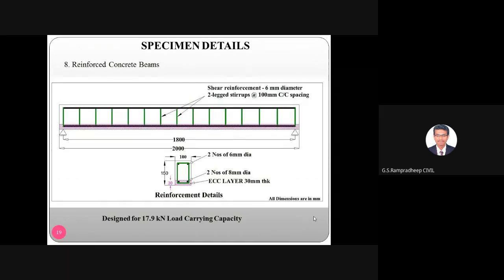And he went for the flexural beam analysis, where you can see the length is 2 meters outer to outer, and from center to center 1.8 meters, a clear span of 1.8 meters. He used 2-legged stirrups at 100 mm spacing center to center, with 6 mm diameter rod. The cross section at the bottom shows an ECC layer 30 mm thick. The remaining place is filled with concrete, the depth of the beam is 150 mm, and the width is around 100 mm. The main rod is 8 mm diameter, 2 rods, and the hanger bar is 6 mm diameter, 2 rods, right?